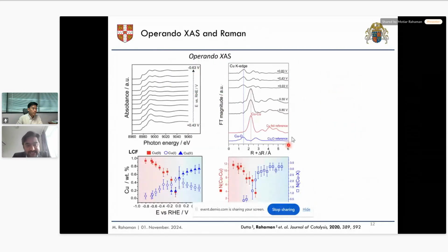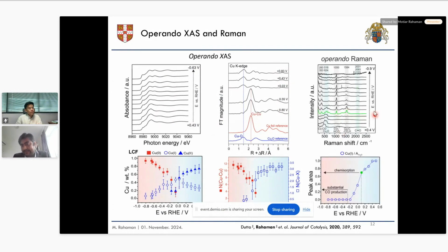Then we directly used this copper oxide as our catalyst. From operando X-ray absorption spectroscopy, with applied potential, when we were going from positive to negative potential, we can see that copper oxide is reducing to metallic copper. Close to zero, we get quite a high amount of copper metal on our catalyst surface. Operando Raman also supports this finding. Starting from a positive potential versus reversible hydrogen electrode, once we pass zero versus reversible hydrogen electrode, all the copper oxide gets reduced to metallic copper, and no copper oxide signal is obtained in operando Raman, similar to operando X-ray absorption.